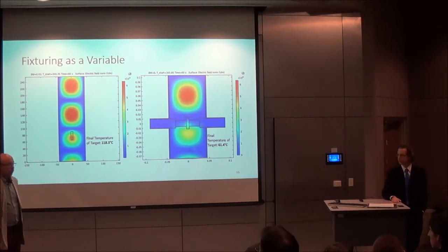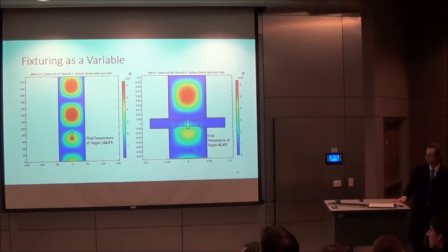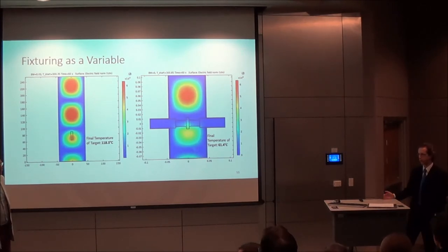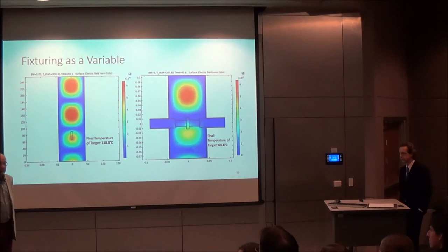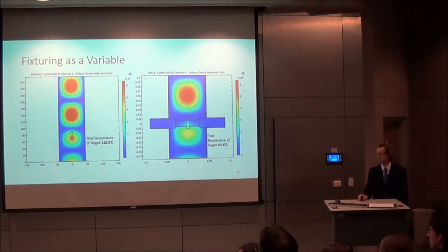Well, we started with those porous foams 6 years ago when the entire project started, and we just kind of dropped it, but the distortion of the field will still be there. Unless they have a low enough permittivity. Well, yeah, we don't know if the compressive strength would be enough. We tried it, and it wasn't that good.